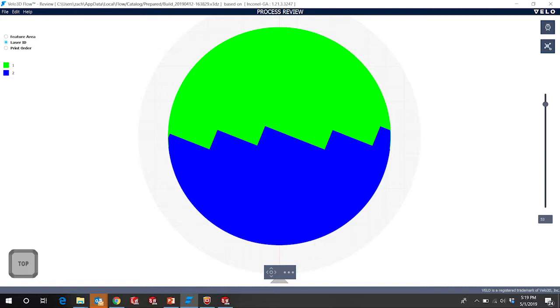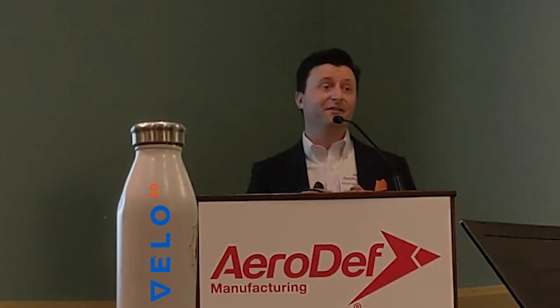So at Velo, we chose a combination of the two that produces the worst possible result if your alignment's not there. What we've done here is split the part into two. This is our 250 millimeter cylinder. We split the part into two, and if you can see it, you actually have green contour coming down around the blue core. So not only are we printing the core with two different lasers, we're actually offsetting it onto the core of the other laser, so that if you have a laser alignment mismatch, it's brutally obvious.